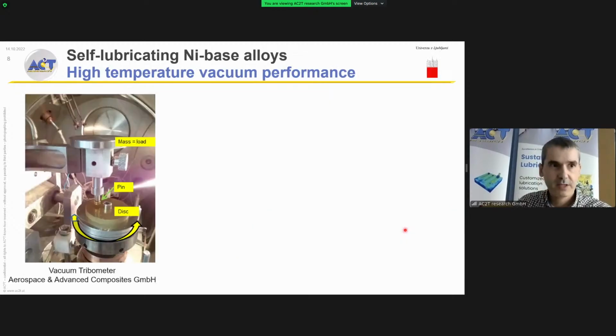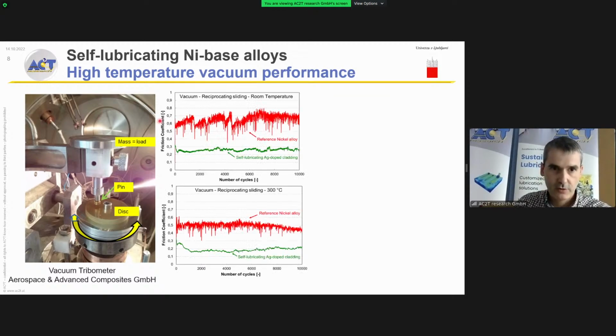But where these nickel-based materials really shine is in vacuum. So in vacuum, we tested against 440C, martensitic stainless steel. This is the reference material for vacuum experiments. And this is a pin on disc, but don't be confused because it's not unidirectional. It's reciprocating sliding, so we are moving around an arc of circumference with a constant normal load and at 2 different temperatures, room temperature and 300 degrees, without any solid lubricant, without lubricant at all. So completely dry contact.